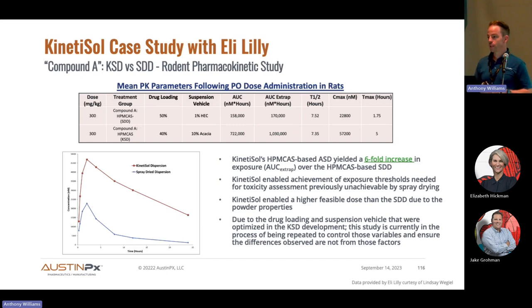Fortunately, Rob and I swooped into Indianapolis. We flew in with our capes on and showed them that Boehringer Ingelheim graph, and they said, if that's real, we really need you to help us out here. So we did, and we did. We did the same thing, basically, effectively duplicating the spray-dried dispersion formulation. They went into their tox study, and fortunately, they didn't just see a 4-fold increase. They saw a 6-fold increase with the KinetiSol dispersion. And obviously, very satisfied with that result.